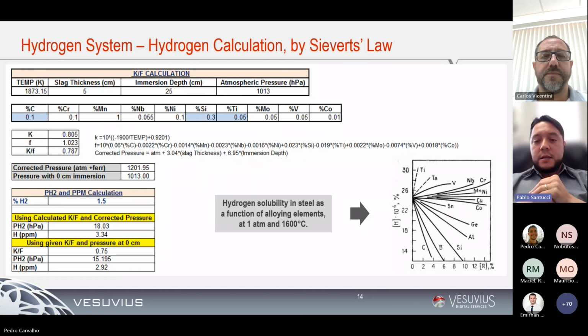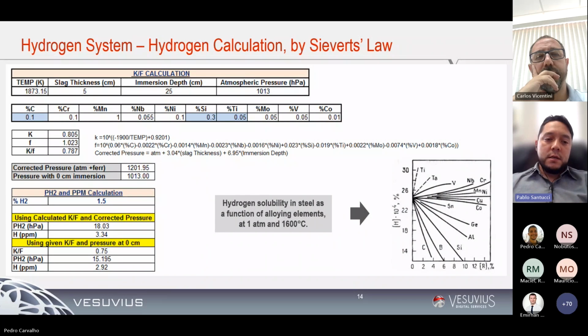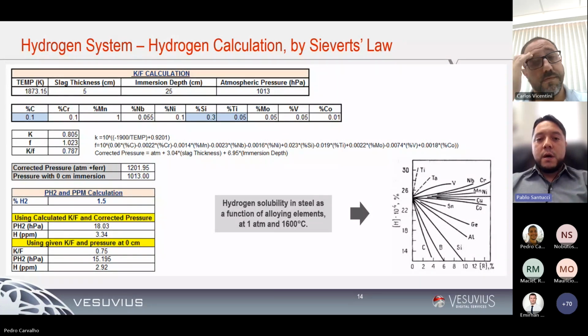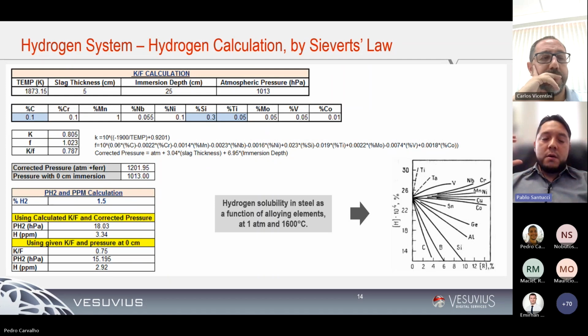And here is another good practice that we also recommend, which is to consider the Sieverts law for these hydrogen readings. Sieverts law is basically what tells us which element can contribute or not in terms of a hydrogen pickup during that measure. But not only that, the Sieverts law can also consider the actual temperature of the steel as well as the referred immersion depth of our probe. So all of these factors can contribute to a better and optimum hydrogen number right after the measurement.